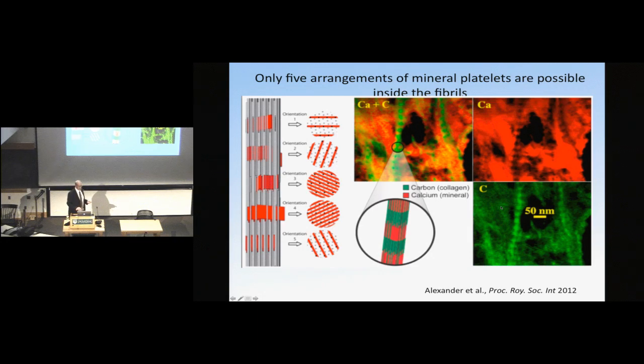And then for the interior, we back this up with a steric model, which showed basically that the staggering, the three-dimensional structure of these collagen molecules, only allows mineral to slide in a few preferred directions, 5 specific directions with a few different volume fractions.